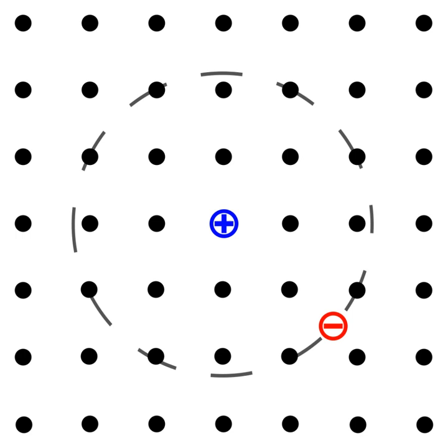Provided the interaction is attractive, an exciton can bind with other excitons to form a biexciton, analogous to a dihydrogen molecule. If a large density of excitons is created in a material, they can interact with one another to form an electron-hole liquid, a state observed in k-space indirect semiconductors. Additionally, excitons are integer spin particles obeying Bose statistics in the low-density limit. In some systems, where the interactions are attractive, a Bose-Einstein condensed state, called excitonium, is predicted to be the ground state. Some evidence of excitonium has existed since the 1970s, but has often been difficult to discern from a Peierls phase. Exciton condensates have allegedly been seen in double quantum well systems. In 2017, Kogar et al. found compelling evidence for observed excitons condensing in the three-dimensional semimetal 1T-TiSe2.